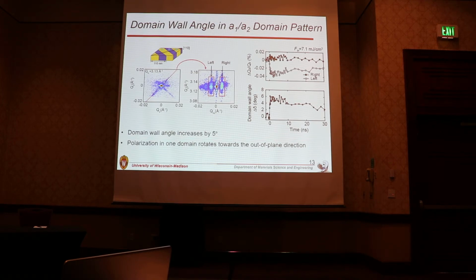Since the domain wall angle is related to the polarization direction in domains, we can understand polarization switching with the domain wall angle measurement. So this is the QX, QY plane, and as you can see before, the domain diffuse scattering of the a1/a2 domain patterns arise. And by taking a look at the QZ, QXY plane in this slide, we can find that the a1/a2 domain diffuse scattering arise at the same QZ wave vector, which means the domain wall is perpendicular to the surface.